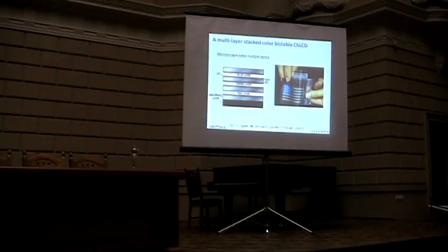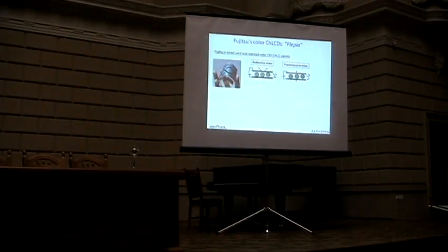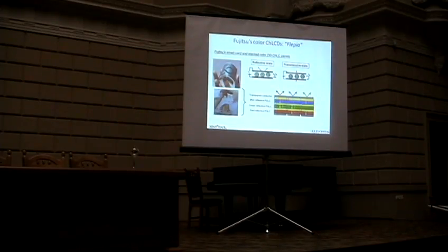And that device is stacked with 3 different layers, and some of these conductive polymer layers get fabricated as electrodes in between the layers, so you can minimize that. That's one area. Well, recently, if you see this Fujitsu, you go to YouTube, you type in this Flepia. The Flepia, they will show you that this type of device has been fabricated into electronic books, electronic readers, and this type of device in general uses 3 layers of these phase separated polymer structures, and then those cholesterics get encapsulated. Kind of a microsphere, and they are in the range of a few microns, 2-3 microns to about 5 micron size. And in that case, you stack them, and then you're using 3 drivers.